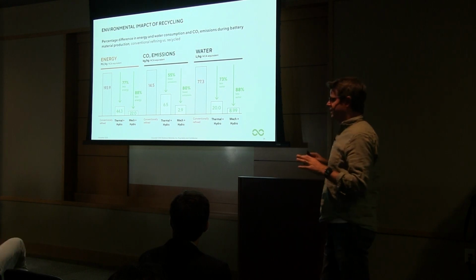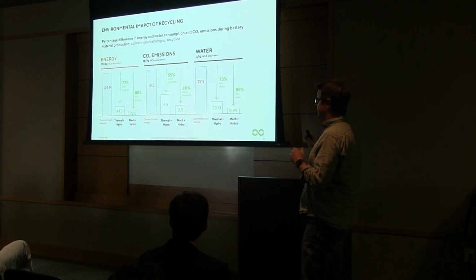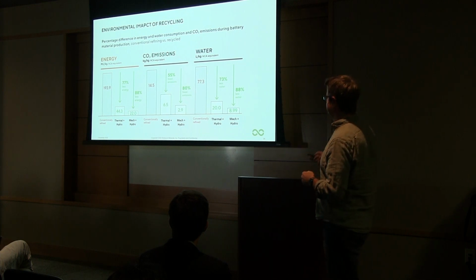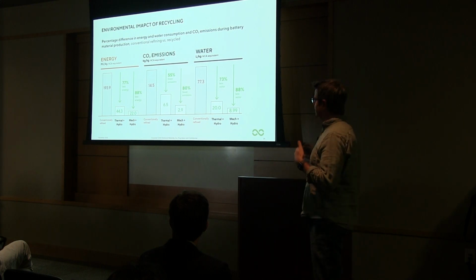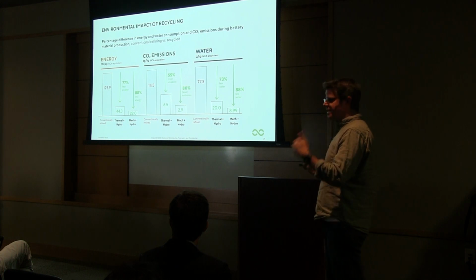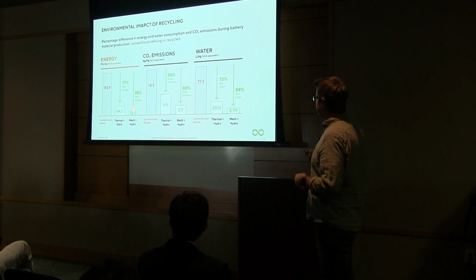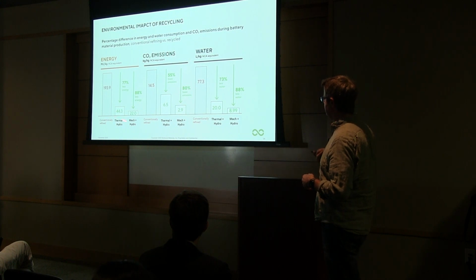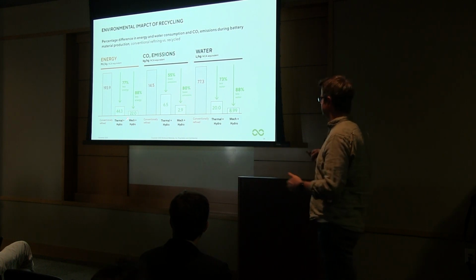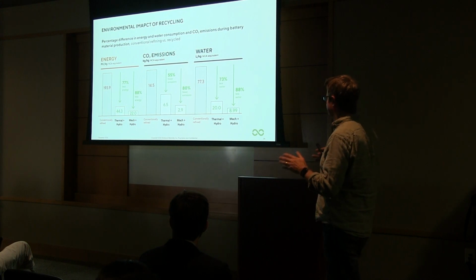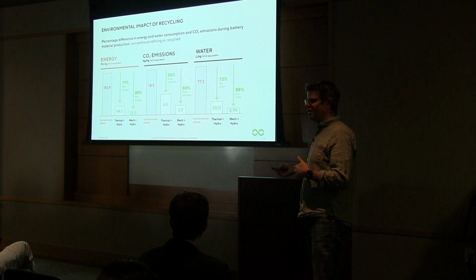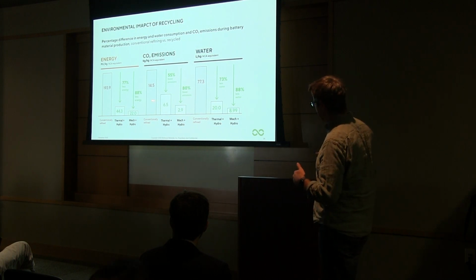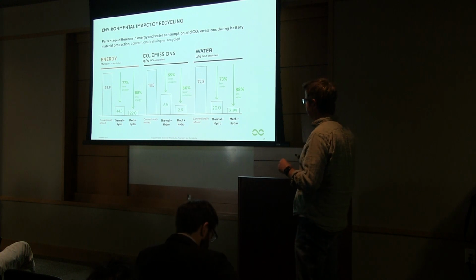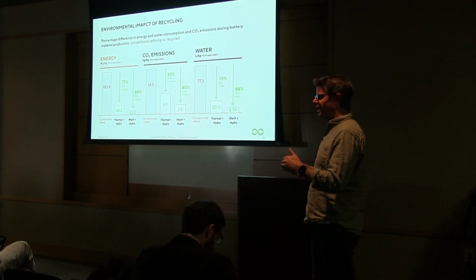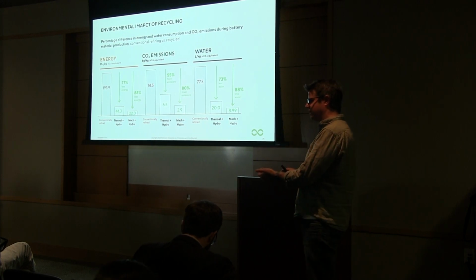Environmental impact of recycling. Now, this is not particularly controversial, because what this graph is showing is the significant reduction in environmental impact, in general, energy, CO2, water, of recycling compared to mining. When you look at thermal processing hydromet, that's our calcination, mechanical processing hydromet, and just our mechanical hydromet, you're talking in the order of 70-80% less environmental impact. And specifically for Redwood's recycling processes, we're probably about 40% lower than typical incumbent recycling flow sheets.